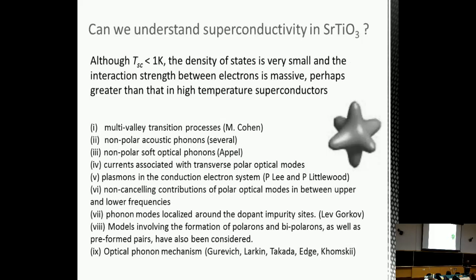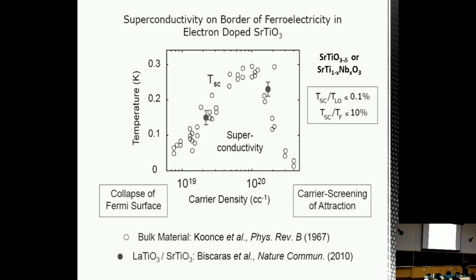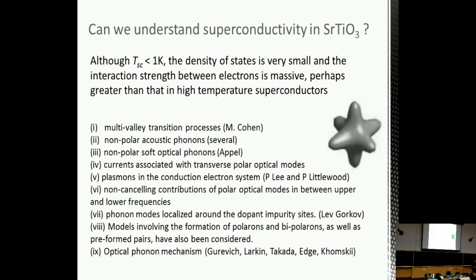So although Tc is very small, less than a Kelvin, the density of states is tiny. And how could it possibly be that superconductivity is being measured below 10^18 electrons per cubic centimeter? How could such a material be superconducting at all? Normally, you would think more like nano-Kelvin or micro-Kelvin, not 1 Kelvin. So that suggests that although Tc is small, the interaction pairing up the electrons is incredibly strong. And if you would scale up the density of states to normal metallic density of states, you would have a superconductor above room temperature. So it's worthwhile trying to understand what is the mechanism for superconductivity in this case.